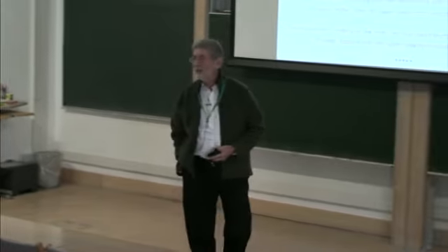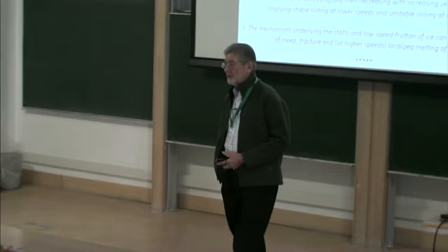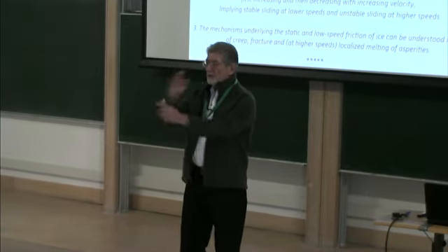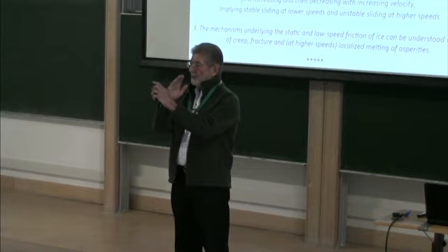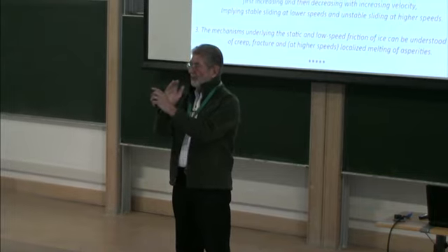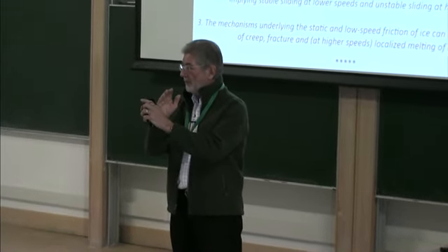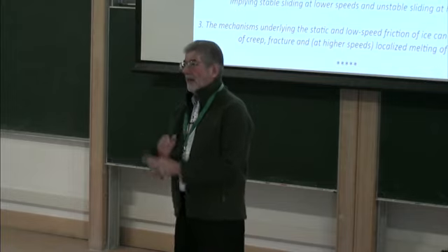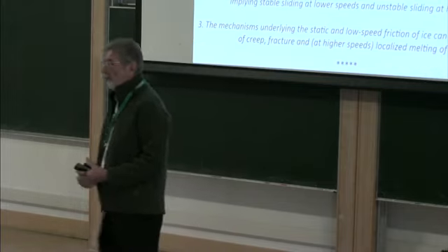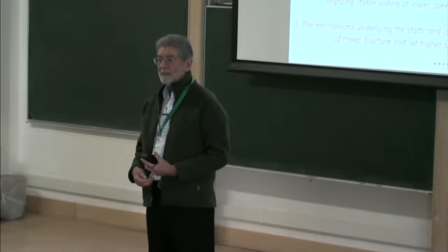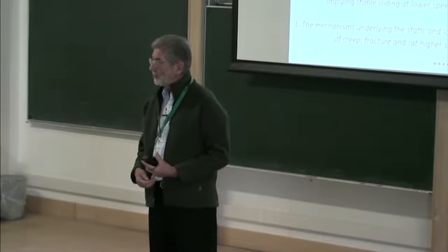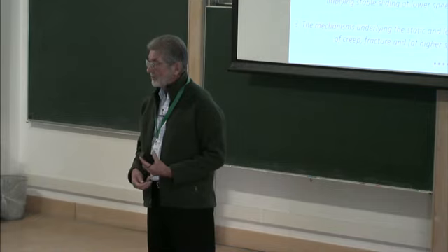It is, Danny. I showed you in that second or third image, I forget, a set of intersecting features which we call intersecting Coulombic shear faults. And the angle there was, I forget, but from that angle deduced a value of the coefficient of friction of 0.9. And I've just spent some time telling you that the coefficient of kinetic friction varies. So surely that angle, if what I said is true, must vary.